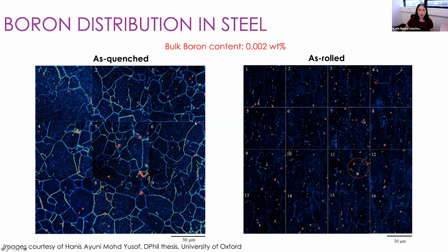So in the as-quenched condition, we can see that the boron is primarily segregated to grain boundaries, whereas on the right-hand side, we can see boron localized to particles and precipitates. So this is another example of the NanoSIMS mapping over slightly larger areas. We can get much, much better statistics from the NanoSIMS than we can with TEM or atom probe when we're looking at, say, grain boundary segregation. We've got hundreds of grain boundaries or precipitates here. And this is all looking at boron at very, very low concentration levels, so much lower than you can actually achieve with SEM, for example, 0.002 weight percent boron in this case.